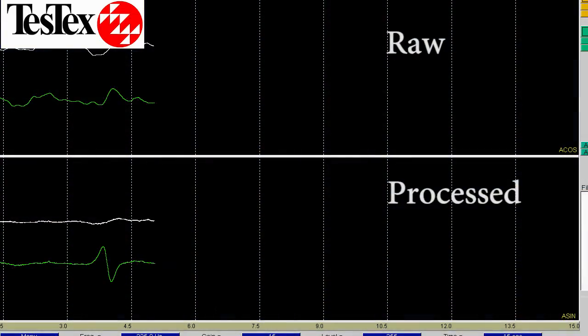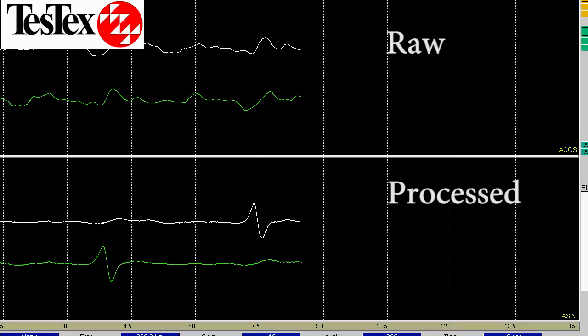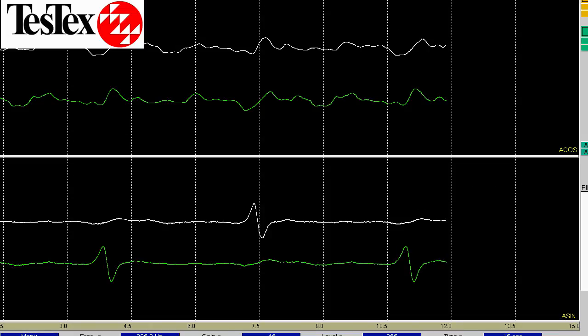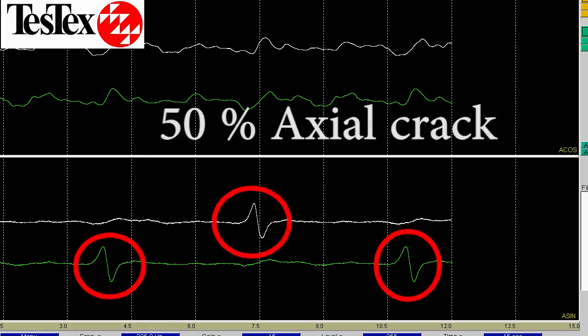The two probes show up as a white and green line, and the crack shows up on both channels in 180 degree distances from each other. This is a crack that measures a 50% wall loss in a tube cut out from a boiler.